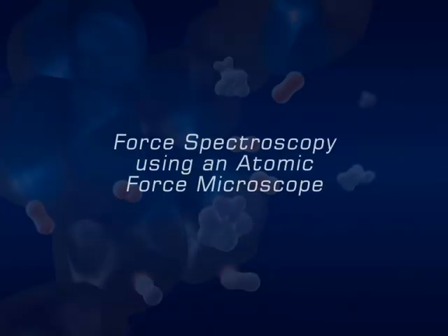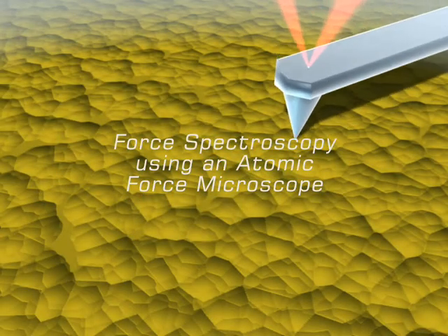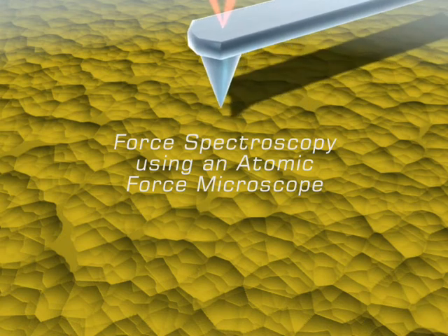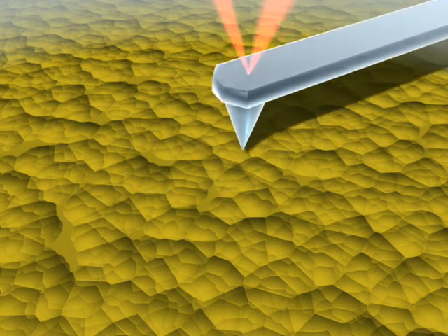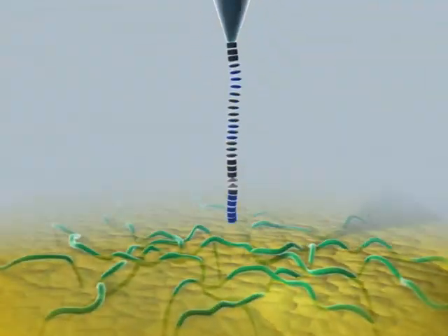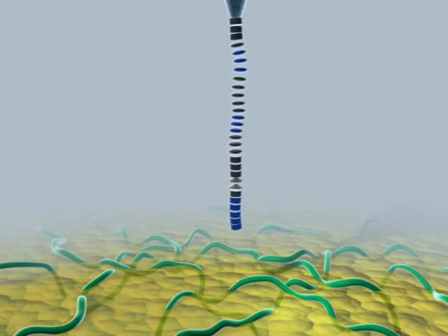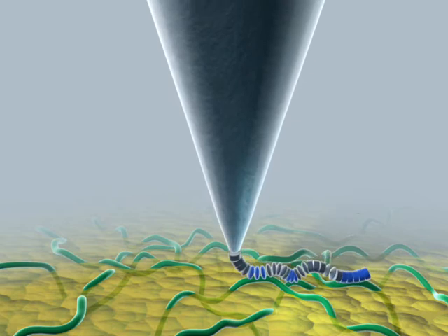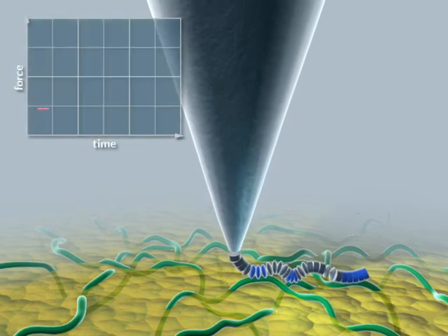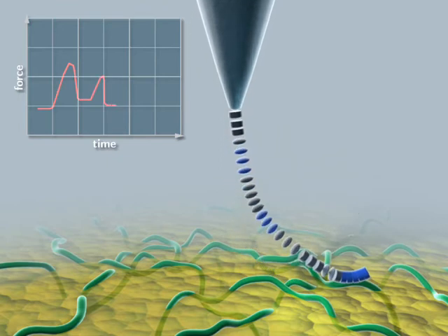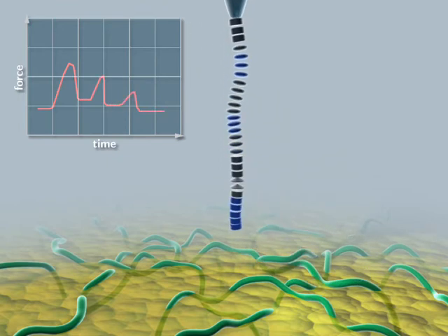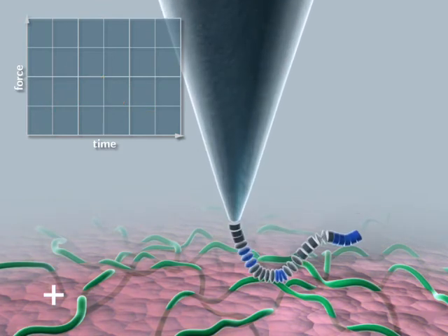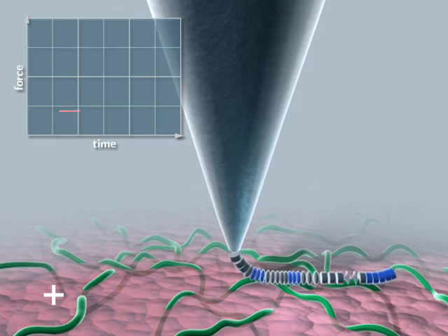By far our most sophisticated measurements and our most exciting demonstration of the ability to control biomolecular interactions using conducting polymers has been achieved using bio atomic force microscopy. Atomic force microscopy provides nanodomain resolution even when operated in water, an environment that is biologically relevant. Recently, protocols that allow us to attach specific biomolecules to these probes have been developed. We then utilize atomic force spectroscopy to measure forces required to pull that molecule off novel surfaces. This provides unprecedented quantitative data on these critical biomolecular interactions.